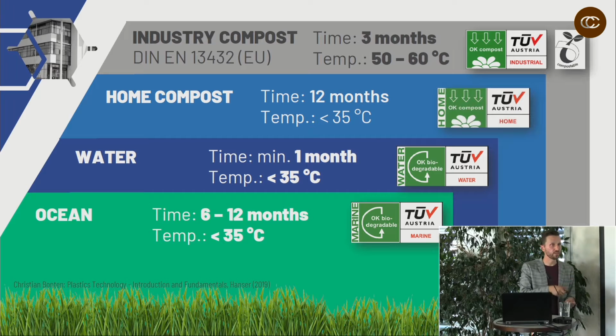Yeah? Most of the packages of the polymers used today, when you have, for example, this compostable sign here on the very left, cannot degrade under normal atmospheric conditions. So that means when you throw it into the garbage in your garden, it will not degrade. You need a certain temperature. Here, that's why it's called industry compostable. We need more than 50 degrees Celsius, and even there we need a certain time. So at least 3 months, and then the polymer is fully degraded.